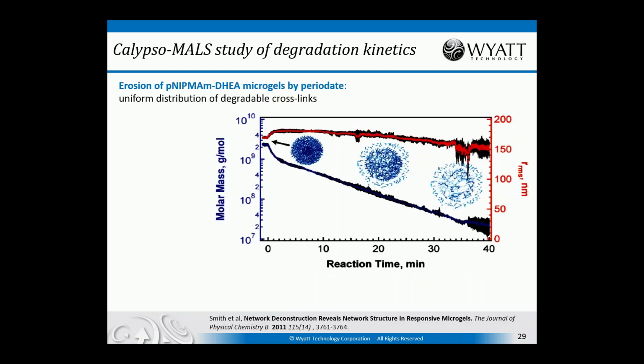And so this is a very nice example of doing just this. Again, this is contributed by Mike Smith, who was with Andrew Lyon at Georgia Tech, looking at some responsive microgels. What they did was take these microgels and mix them with periodate, which causes their erosion. It basically degrades the crosslinks within the polymer.